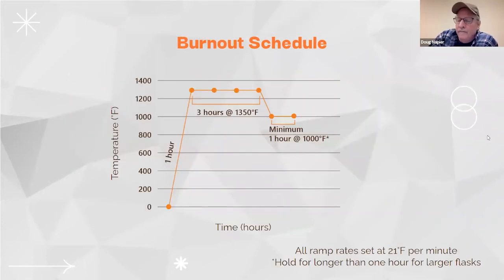And so, burnout schedules on B9, they have a burnout schedule that they suggest, and I use that quite a bit. But I seem to have pretty good luck with my own burnout schedule, which is like 5 or 6 hours. So what I will do is once I have my piece cured, I will invest it and let it sit aside for a minimum of an hour to an hour and a half.